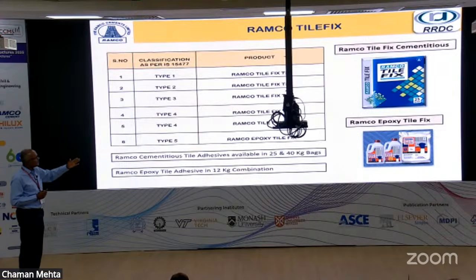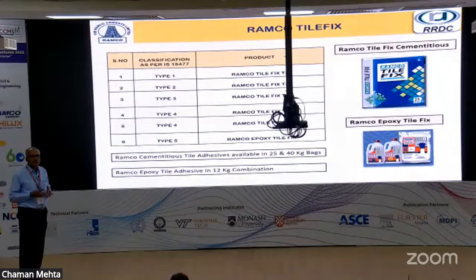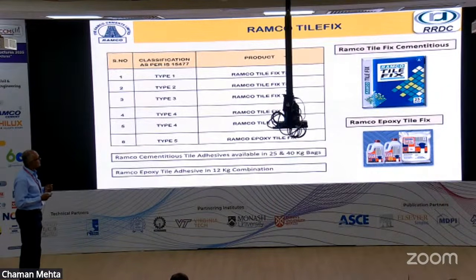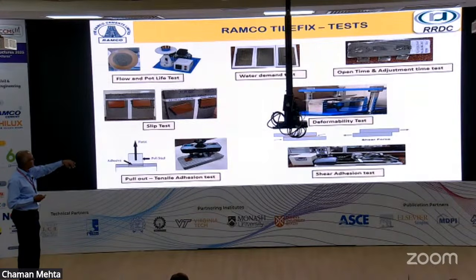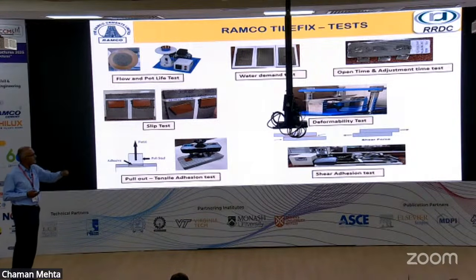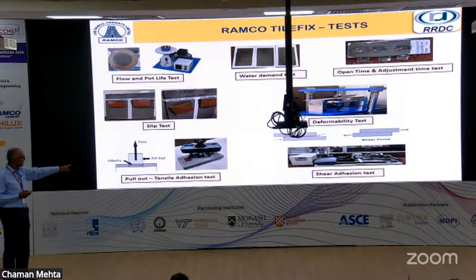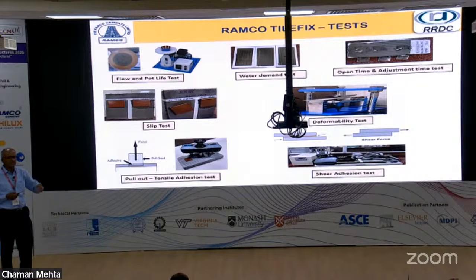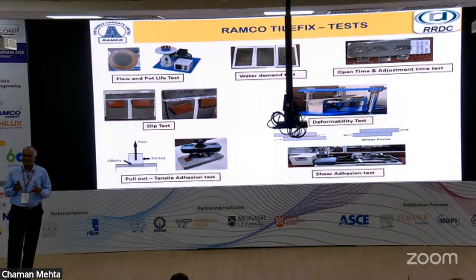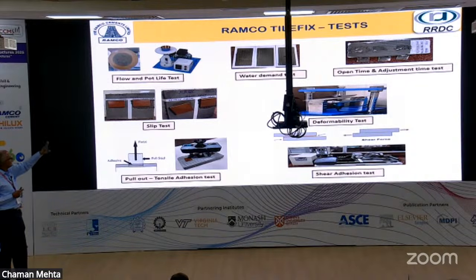The one development that we have done recently is that there has been a demand for epoxy tile fixes because of the kind of adhesion that is required, and they don't want to take much risk as far as the tiles are concerned. So we have developed that. The test of interest is the deformability test. The basic tests that we do are tensile adhesion and shear adhesion strength, as far as the tile fix is concerned. So these are the kind of tests that we do.